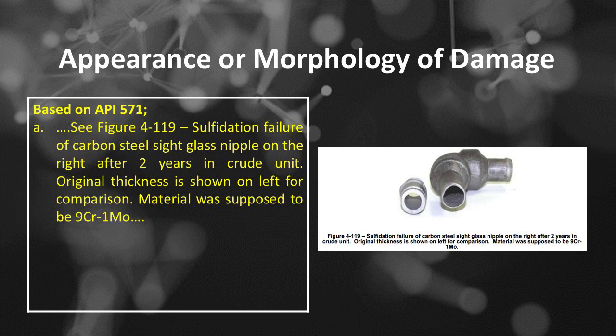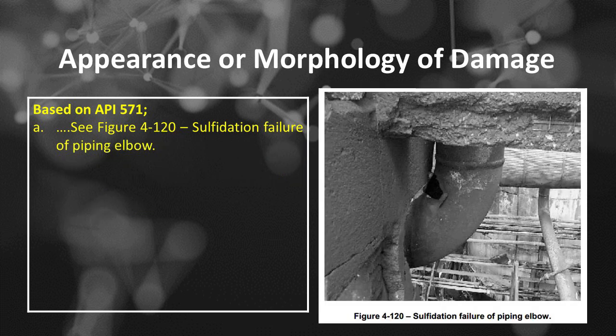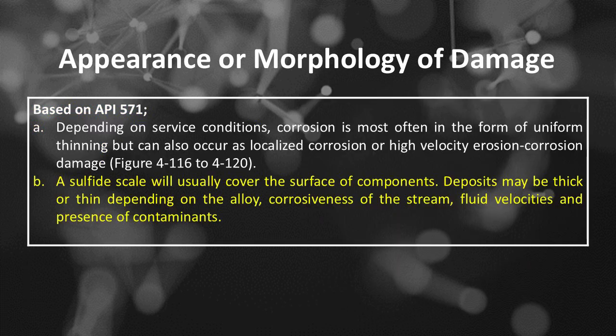See Figure 4-119, sulfidation failure of carbon steel sight glass nipple on the right after 2 years in a crude unit. Original thickness is shown on left for comparison. Material was supposed to be 9Cr-1Mo. See Figure 4-120, sulfidation failure of piping elbow. Number B: a sulfide scale will usually cover the surface of components. Deposits may be thick or thin depending on the alloy, corrosiveness of the stream, fluid velocities, and presence of contaminants.